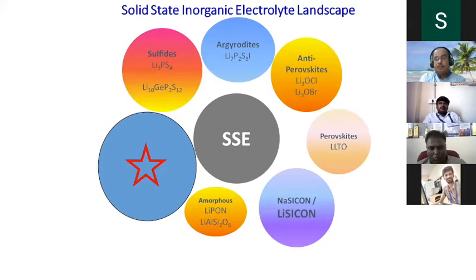So if you look into these solid state inorganic electrolyte landscapes, sulfides are the best option, then maybe argyrodites, and antiperovskites, which was introduced by a professor. Good enough, he still claims it's the biggest invention, but there is a lot of controversy regarding antiperovskites. Then perovskites are good conductors, unfortunately with a lot of grain boundary resistance. And you have titanate, which is not stable against metallic lithium. NASICON and LISICON offer life in many materials.